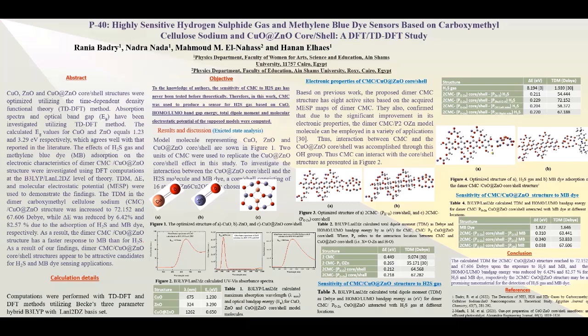Table 3 and Table 4 presented the obtained values of the total dipole moment and HOMO-LUMO band gap energy for the CMC structure core shell interacted with H2S at the different positions and with the methylene blue dye at the same positions. It's clear that the values of total dipole moment and the HOMO-LUMO band gap energy differ by changing the position of the interaction, which means that the proposed structure of CMC and core shell structure is more sensitive for the H2S gas and methylene blue dye.